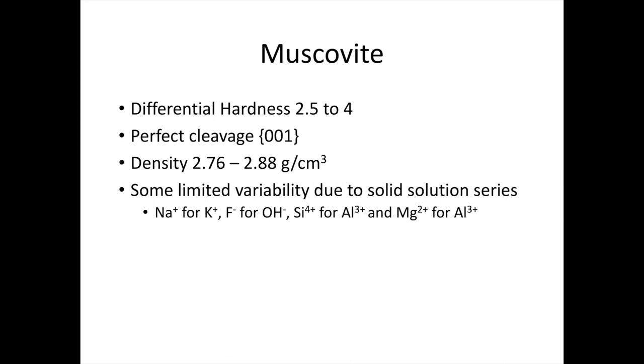We should also mention that muscovite isn't a particularly dense mineral. The density varies between 2.76 and 2.88 grams per cubic centimeter. And this variability in density, much like the variability in our refractive indices, is caused by the limited solid solution series that can occur within muscovite. So for our muscovite, some of our interlayer potassium can be swapped out with sodium. There can also be substitutions of fluorine for hydroxide. And there's also more complex coupled substitutions involving silicon, aluminum, magnesium, and sometimes iron. And there's also some other minor substitutions that can occur in this structure as well.